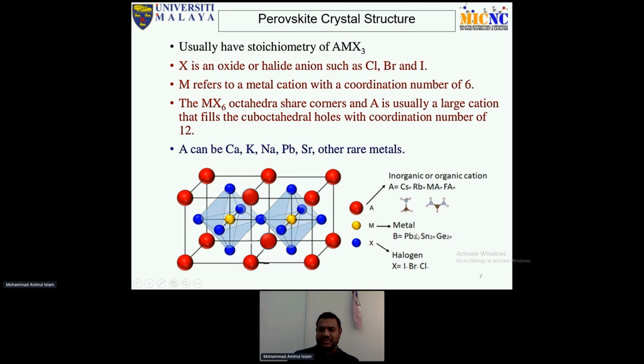So how to change the lead, the toxic material, to green or non-toxic materials and still get high efficiency. Also in case of A, we say that A is primarily methylammonium. Now methylammonium lead halide is sometimes called... Primarily the perovskite solar cell uses this methylammonium, but later on people tried to change this methylammonium to cesium, rubidium, even formamidinium, and also calcium, potassium, sodium. Then other materials could also be possible.